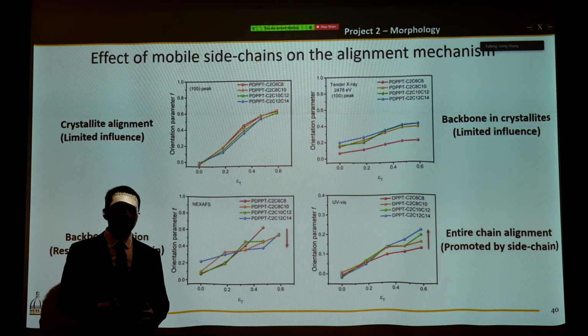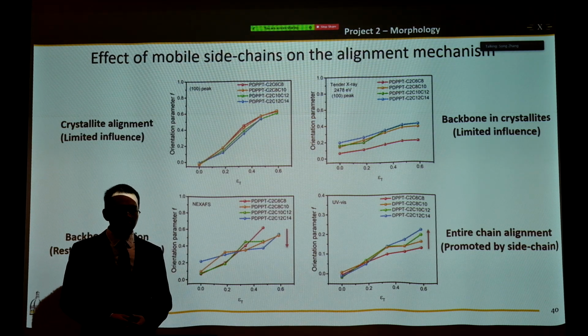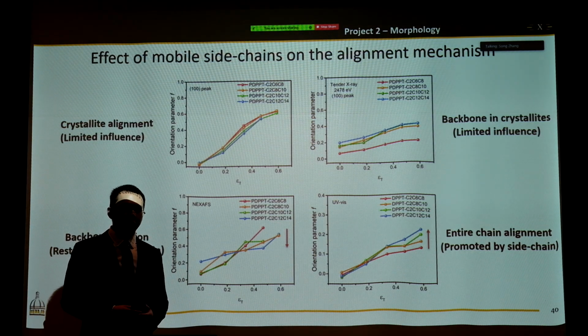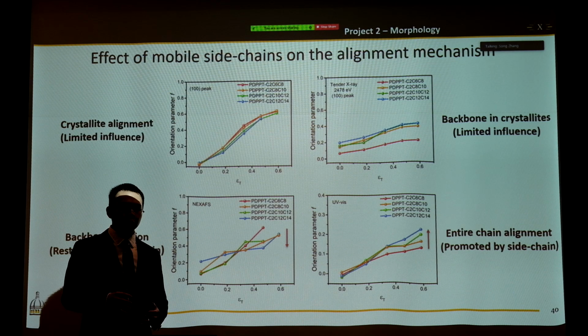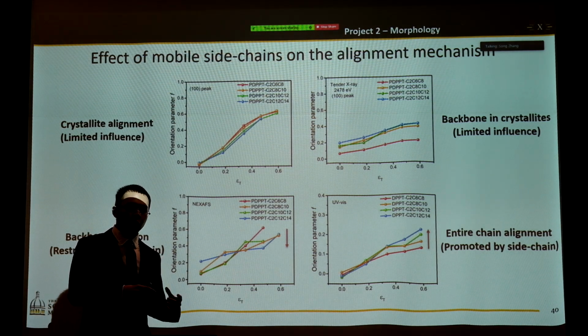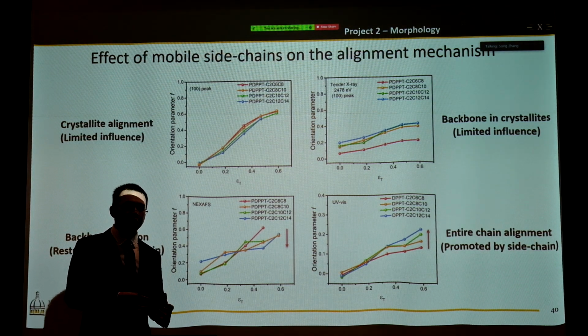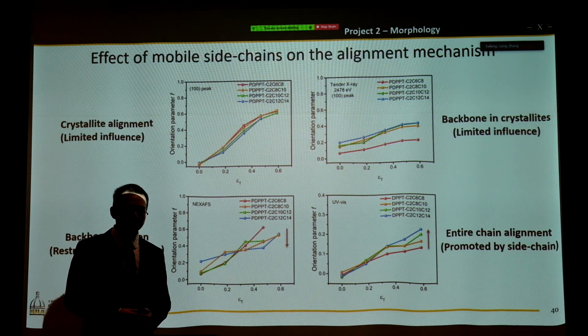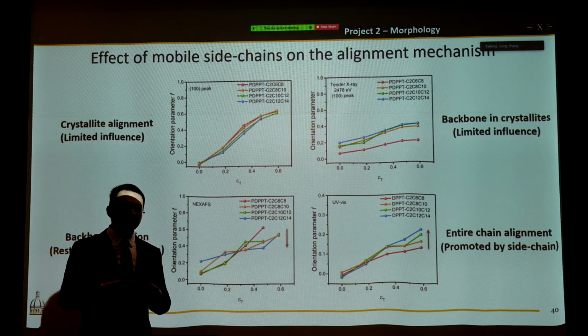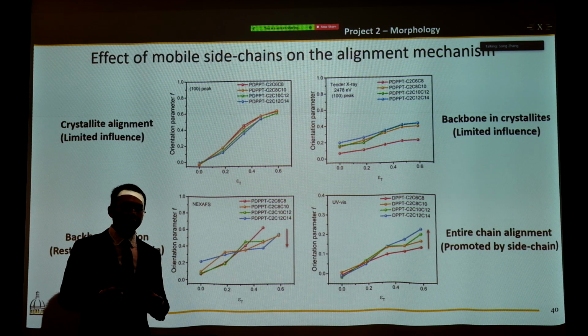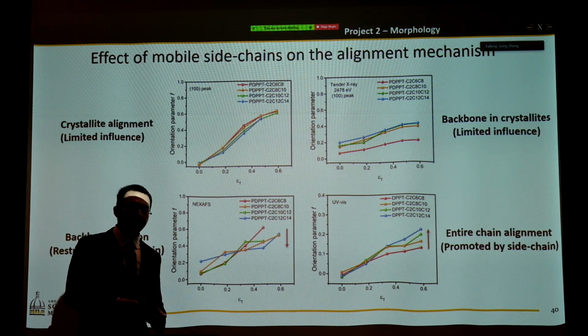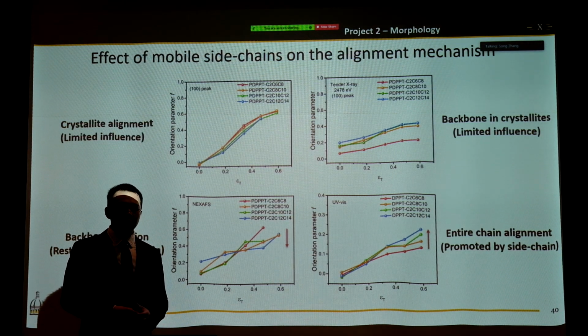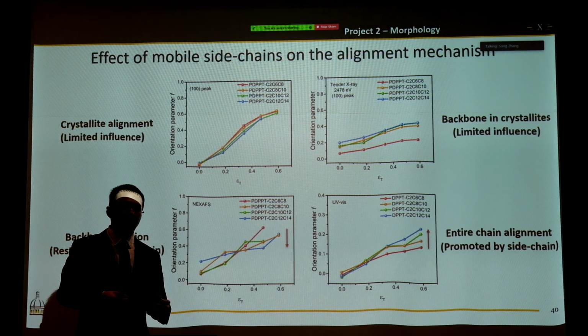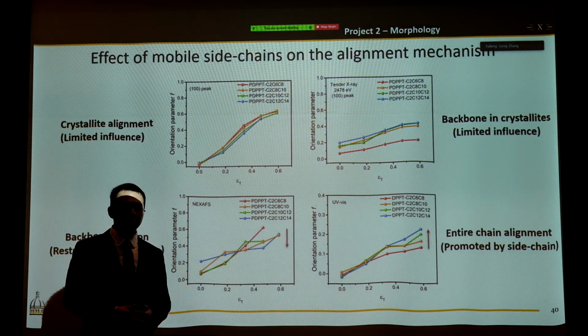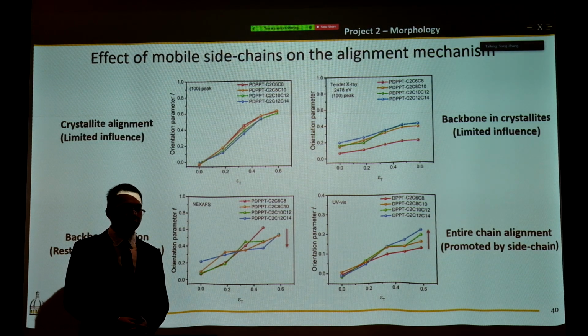Now let's talk about the effect of side chains, as I promised. Based on the four different techniques I talked about, the top two curves show how the crystalline orientation is different for different side chain engineered DPP polymers. And the answer is that the side chain length does not necessarily change the alignment mechanism of crystalline domains. It still has rotation, and it still has backbone extraction to a similar degree. However, in terms of spectroscopy techniques, we saw some difference.